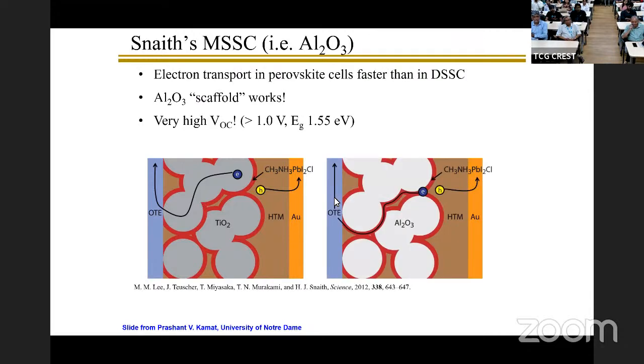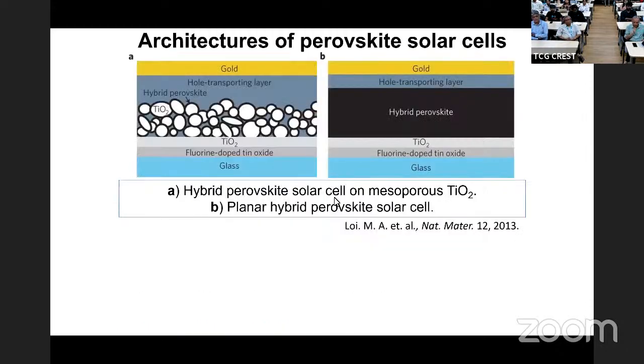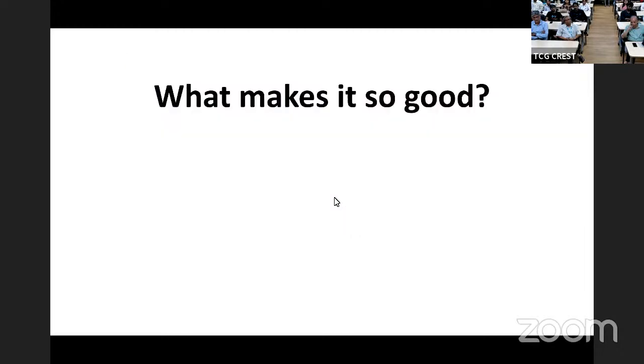Very quickly, Henry Snaith found that if you replace the TiO2 with alumina, which is absolutely no good for conducting electron or hole, the efficiency didn't change, which meant that this dye material, this perovskite that I'm talking about, is also a very good conductor of electrons. And it turns out it is a very good conductor, with very high mobility for electron and hole both, such that the device architecture went from this mesoporous TiO2 covered with the dye to a solid block of the hybrid material, which can then absorb photons in a very thin layer of it. And then you take the electron out this way, hole out that way, and that made the entire device structure much more simple. So basically, it revolutionized the way we think about solar cells.